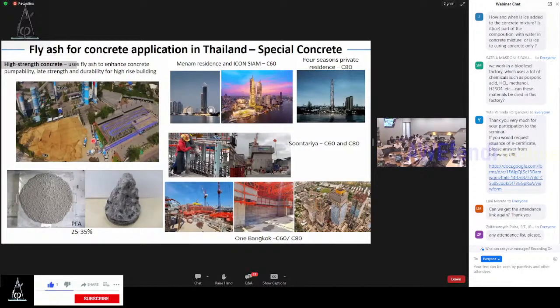And we even tried to make a pump simulation for the concrete. You can see here the pump line. The distance of the pump line here is about 600 meters. We pump the concrete in and we observe the concrete out with no problem when we use fly ash like this. So there are many applications in Thailand where we use fly ash so far. Right now we generally use C80 for high strength concrete in Thailand.